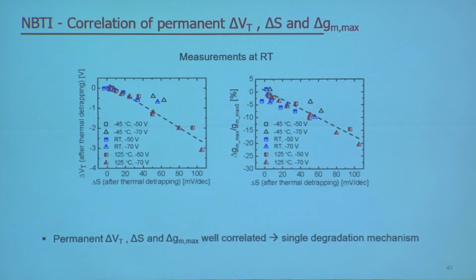So here is the correlation of all three parameters in one graph, and in here I also add all the temperature data that I didn't get a chance to show you. But as you can see, ranging from -45 degrees C to 125 degrees C and -50 volts to -70 volts, all the data we have here have a very nice linear correlation, which again suggests a single degradation mechanism for this NBTI at high stress regime.